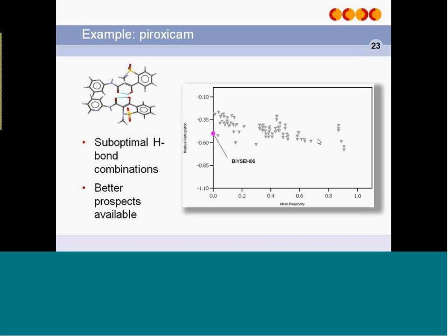And again, if we look at the solid state for this polymorphic piroxicam, you can see it has an intramolecular interaction, but there are good donors and acceptors that aren't participating at all. Hence, it's viewed as being a less stable outcome. And again, if you were in this situation in the development scenario, then this would be a warning sign. You probably need to go back, look at the experimental results, see if there are other polymorphs out there which are likely to be more stable prospects.